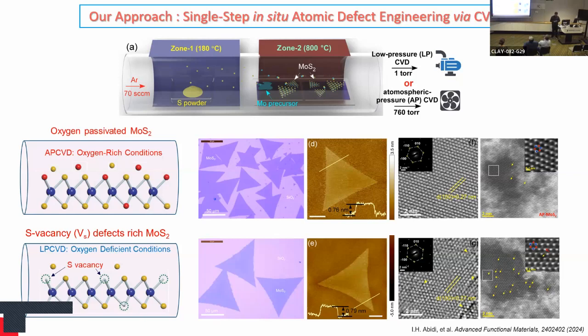In terms of AFM also, you can see it's a single layer, and the thickness is kind of similar. But once you go to the atomic level, you can see there are more defects in the one I grew under low pressure CVD conditions. Once we use APCVD, the defects are lower. So this is interesting, happening once we just change the conditions of the growth.